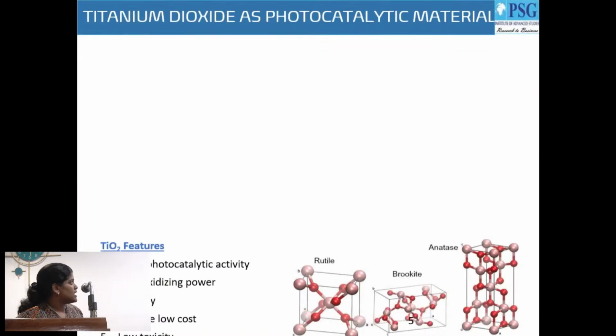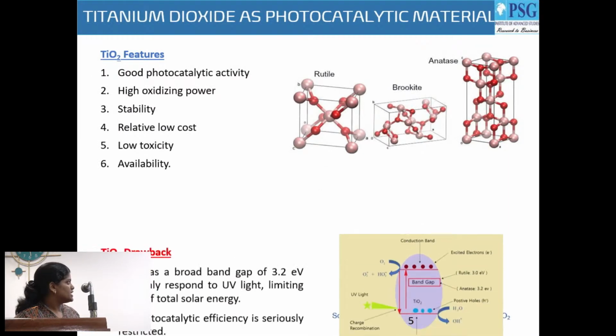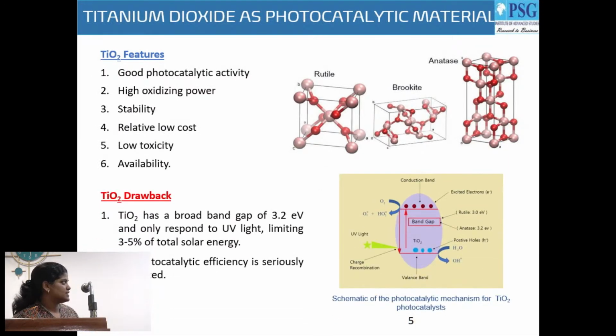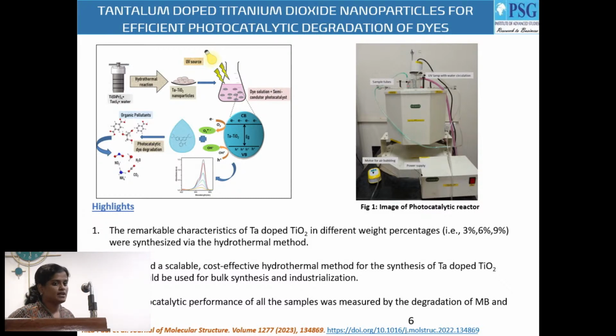Titanium dioxide as a photocatalytic material, these are the features, and these are the three different phases of TiO2. The main drawback is its wide band gap. It limits use to 3 to 5% of total solar energy, and its photocatalytic efficiency is seriously restricted. So this is the work I am going to present, tantalum-doped TiO2 for efficient degradation of dyes, and this is the photocatalytic reactor that we have been using for degradation of dyes.